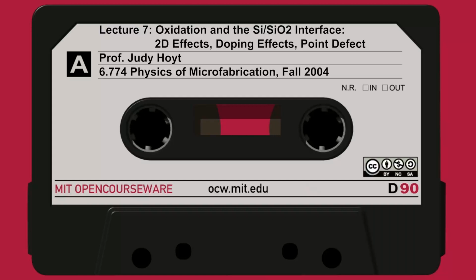So in this model, you can see what's happened is the field oxide has encroached in. The mask edge starts here at x equals 0. It's encroached in from x equals 0 by about, say, half micron. So the oxidant has diffused in here, and it has oxidized underneath the nitride. So you have this region where the silicon is sloped, and the encroachment distance I would quote here as being half micron. So your active device really starts here, in this region.